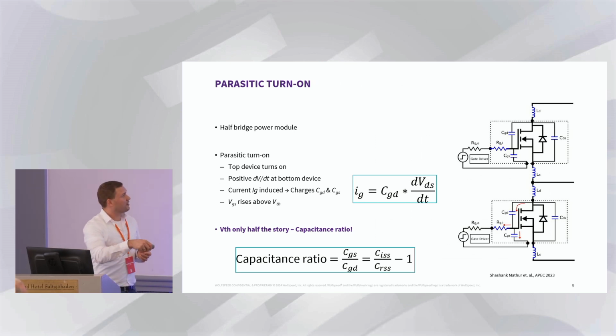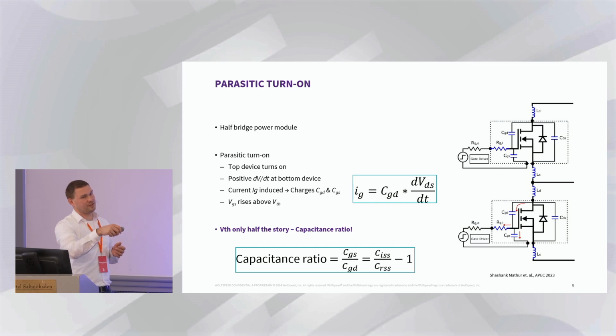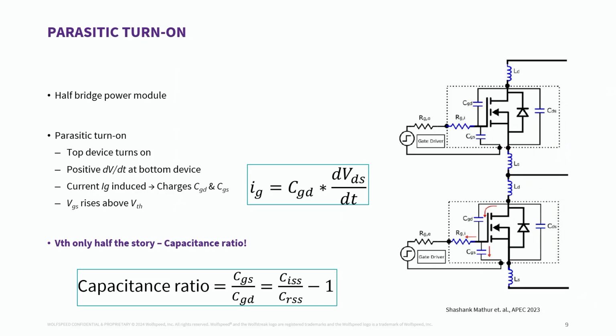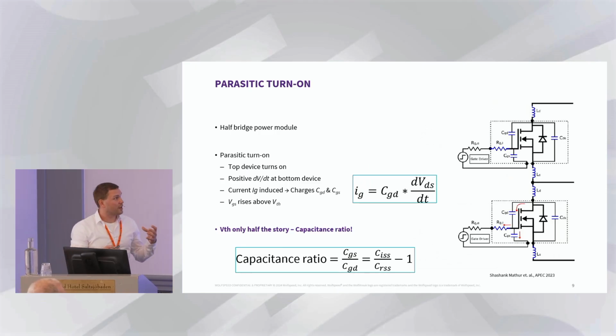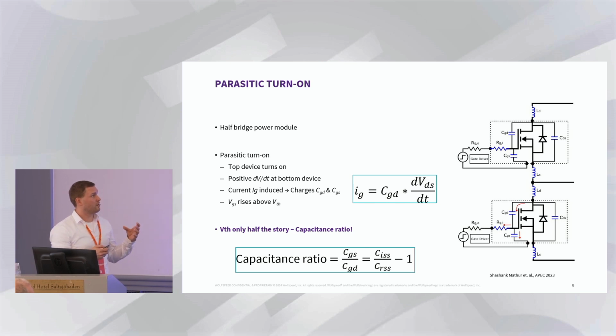Parasitic turn-on, and let me start here with VTH is only half the story. We have the threshold voltage, it has a negative temperature coefficient, which means the higher the temperature, the lower the VTH. However, this is only half the story because the capacitance ratio matters. Once you need to charge the capacitances to make the device switch on, right? And if you have a certain value for the capacitance ratio, you really make the device resistant to a parasitic turn-on because it still needs time to charge the capacitances until the device turns on. Which means even though you are already maybe above the VTH, it doesn't necessarily mean that the device is turned on.